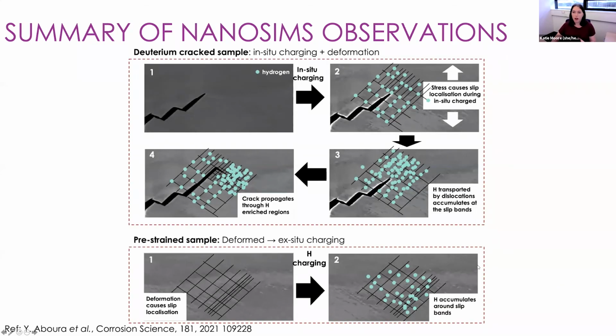So just to summarize all of those observations: in our in situ charging and deformed sample, we introduce some deuterium into a cracked sample. The stress that we're applying to it causes dislocation slip bands to form, and we can see deuterium localizing to those dislocation slip bands. The hydrogen is going to be transported by those dislocations, and it's really going to start to accumulate at those dislocation slip bands.